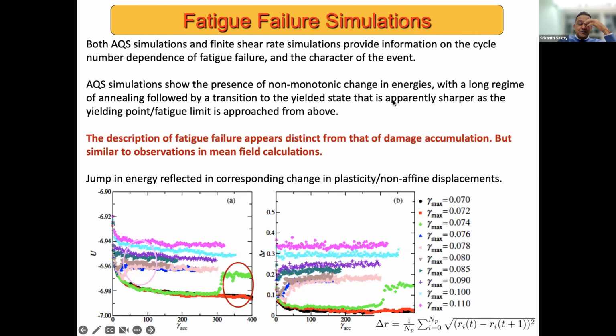So the next 5 minutes, Shubha, is that okay? I'll spend on going back to simulations and describing some of the results that we have. What I show here are results from AQS simulations at a number of different strain amplitudes, starting with very high initial energies. And what one finds is this curious behavior, focus on the green curve here, where the energy goes down, indicating that the system is getting annealed because of mechanical deformation, up to a point, highlighted with these circles, at which a sudden up jump in the energy indicates that the system has yielded. This kind of behavior is also visible at other strain amplitudes, which are bigger, and it happens at an earlier time.